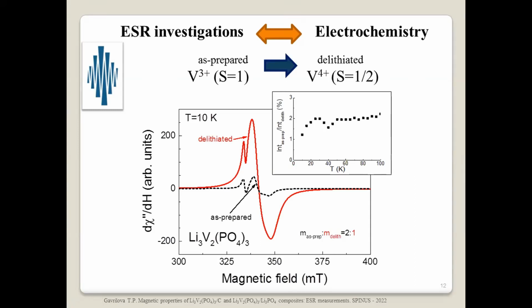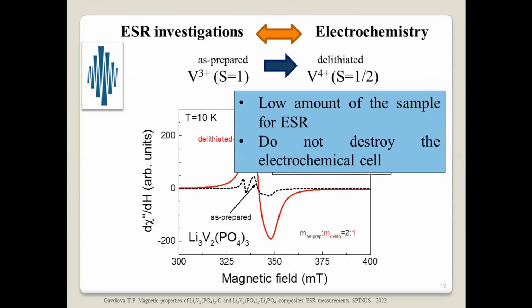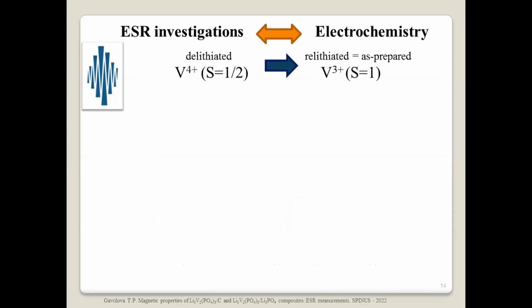And at this moment, I can say that to perform ESR measurements, we need a very low amount of the sample. So we do not need to destroy the electrochemical cell. We do not need to perform magnetization measurements to check the valence state of vanadium. We can take this very low amount of the sample and then continue our electrochemical measurements. So, charge, then discharge of the electrochemical cell, and we perform the relithiation process.